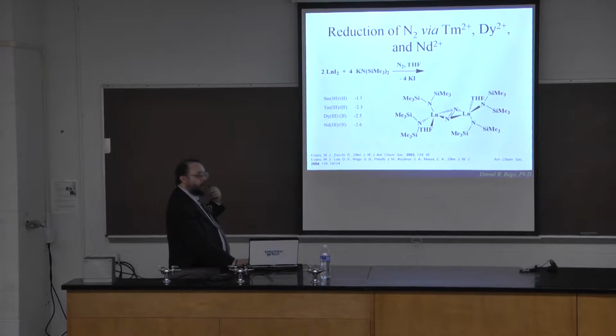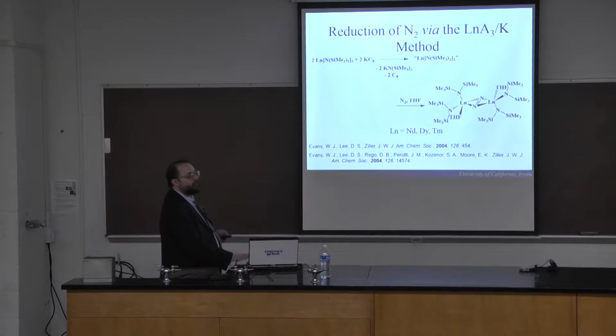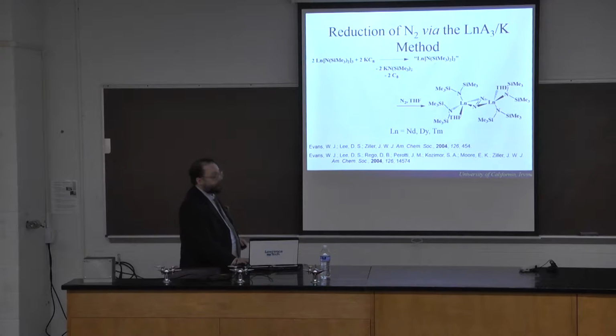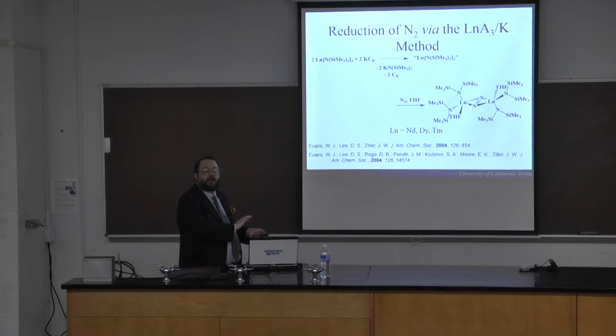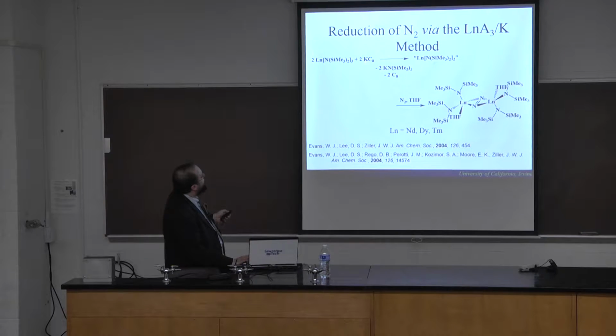It turns out that with more powerfully reducing lanthanides, they will irreversibly bind. So for example, a divalent lanthanide diiodide with the potassium salt of bis-trimethylsilylamide, this ligand here, under dinitrogen will form a dinitrogen complex, and you're basically losing potassium iodide by forming a lanthanide amide bond. And it turns out you don't really need a divalent starting material. They're kind of a pain to make, and at the time you just couldn't get them for most of the lanthanides. Start with a trivalent, this is a 3+ tris-trimethylsilylamide, and here I use potassium graphite, basically potassium dissolved onto graphite. It helps disperse the potassium, allows it to react a lot more efficiently. So the potassium oxidizes from 0 to +1, reducing the lanthanide from +3 to +2, and then that reduces the dinitrogen to form this compound.